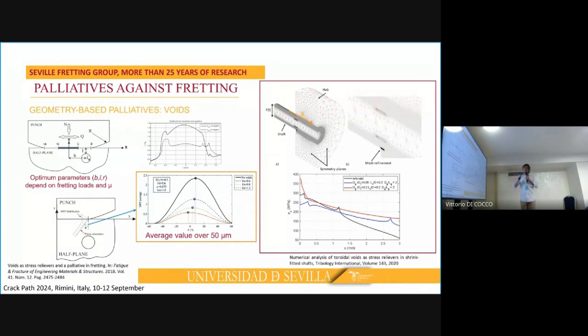In this case, the important thing is that when you introduce this void, an important redistribution of the contact surface stresses is produced. Due to that, an important decrease of the contact stress field below the surface is produced. And here we can see, for example, some results.